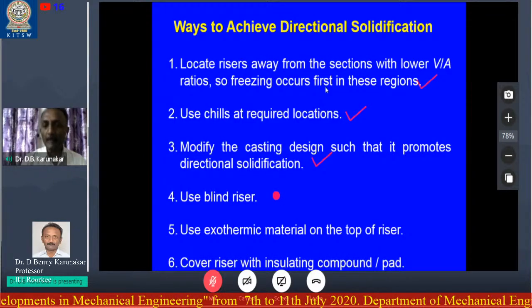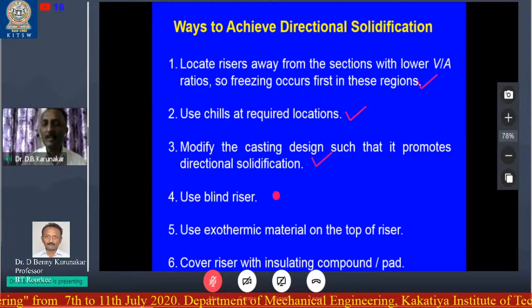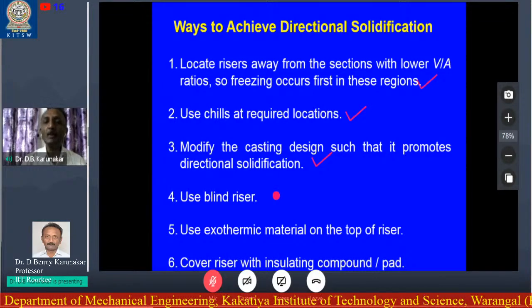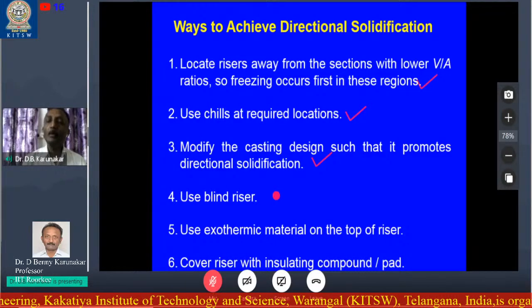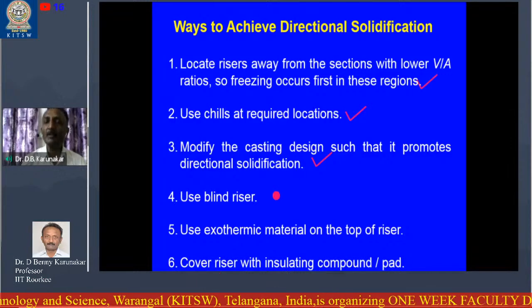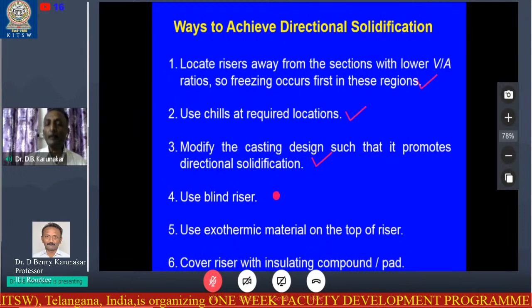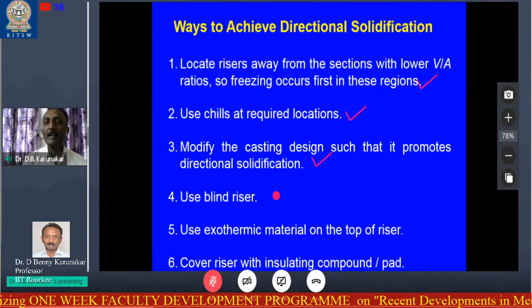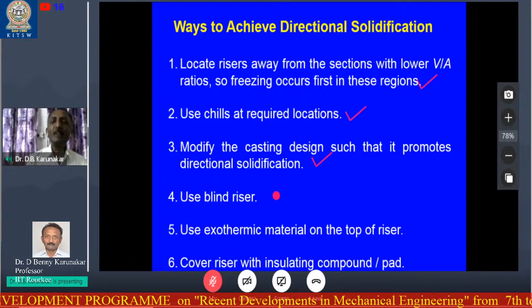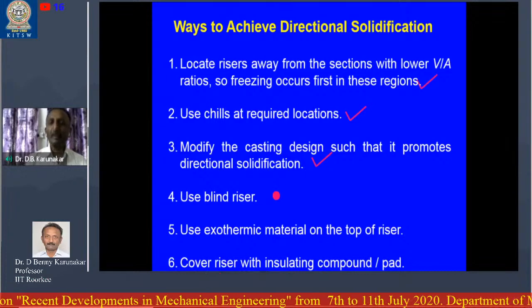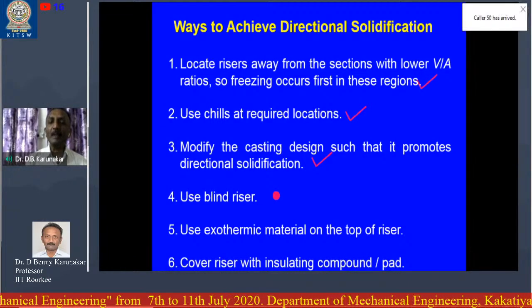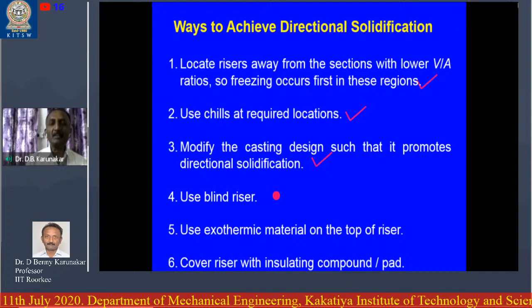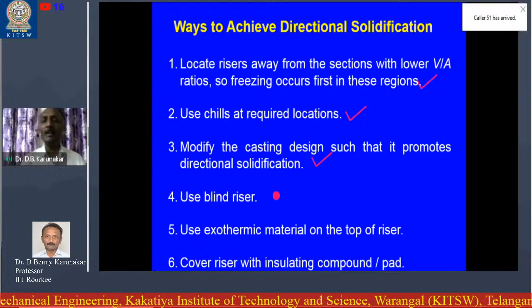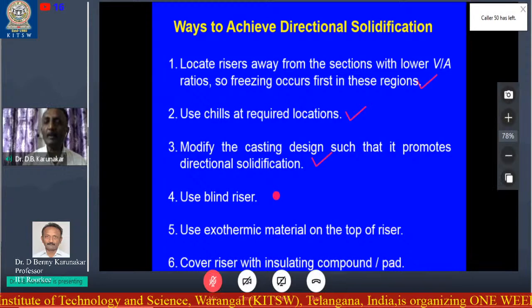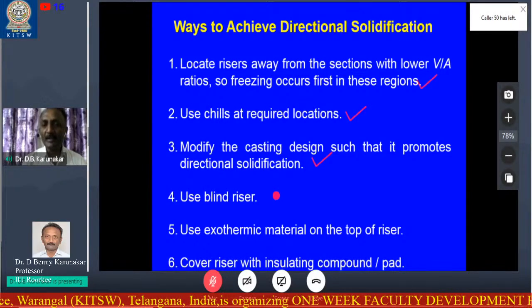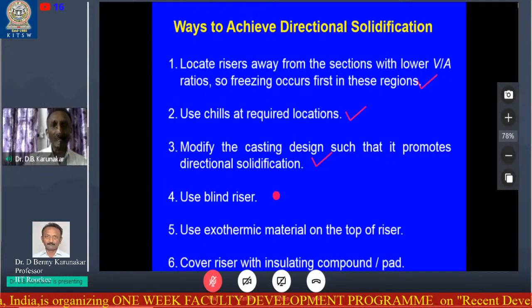Next, use the blind riser. The prime reason for the shrinkage defect is insufficient molten metal in the riser. Do you know one fact? The efficiency of an open riser is only 15%. Meaning, suppose there is 1 liter of liquid metal in an open riser, only 150 cc is used for feeding the casting. The remaining 850 cc is underutilized, because before it can feed the casting, it solidifies. The efficiency of an open riser is only 15%, but we can't avoid the open riser because it gives us an indication that the casting is being fed with molten metal.